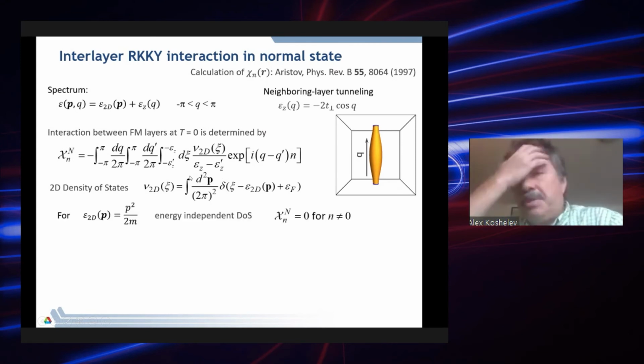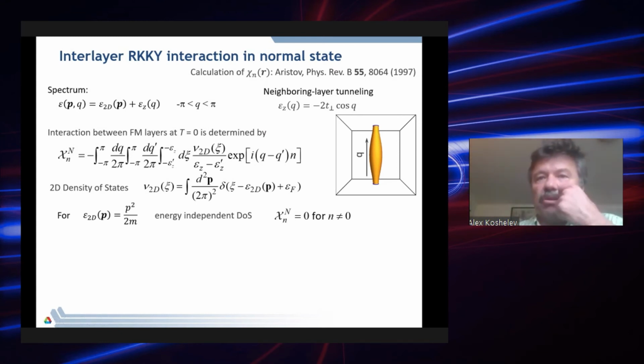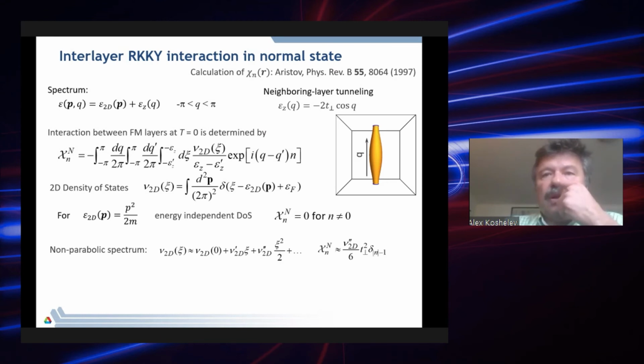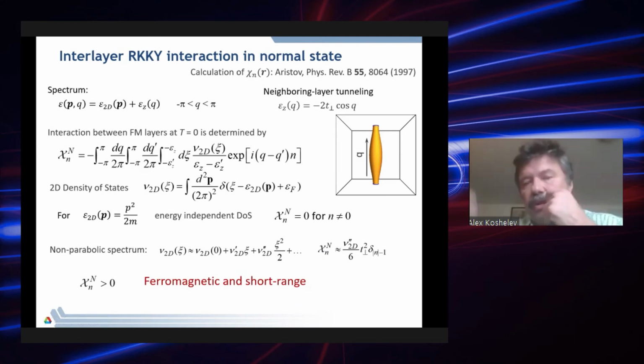And if we consider simple parabolic spectrum, we obtain from this formula an immediate result that actually there is no interaction between layers in the normal state. To have finite interaction, you need some non-parabolicity, which makes the two-dimensional density of states energy dependent, and the interaction is proportional to the second derivative of the two-dimensional density of states with respect to energy. So the simple take-home message is that the normal state RKKY interaction in a layer system is ferromagnetic and short range, and this is already very different from the classical textbook result in three-dimensional material.